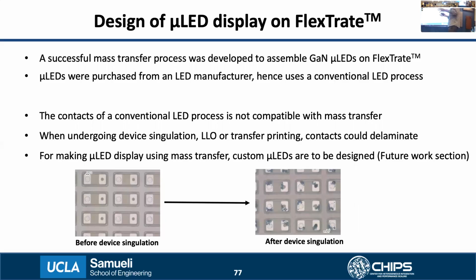dice up the device without removing the GaN from the sapphire and then package it in epoxy. So this conventional LED process is not actually compatible with device singulation, LLO, or transfer printing, which is typically used in mass transfer, as the contacts could easily delaminate during these processes because of the high stresses involved. So you can see in the images in the bottom that before singulation, the contacts on the devices are intact. But after we start singulating these devices, you notice how the contacts begin to delaminate.